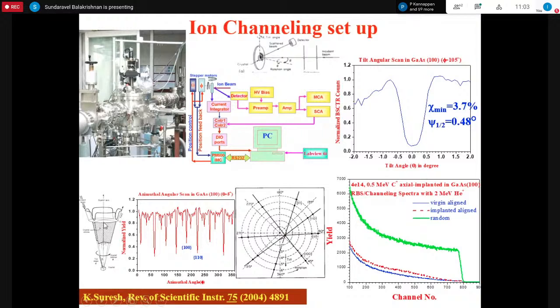This is the normal direction, and from the normal direction, we tilt the sample by 5 degrees. By tilting at 5 degrees, for a fixed charge, we collect the backscattering counts. For example, this is the Rutherford backscattering spectra for gallium arsenide, and in the bottom right side we are seeing this Rutherford backscattering. This green one corresponds to the random spectra for gallium arsenide.